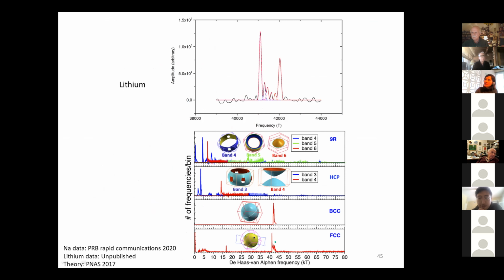So that's one of the things that we get inspiration from. But really the main reason that we're looking at these is way beyond that. We really want to understand what the Fermi surface of these metals looks like and how it changes with pressure. Fermi surface nesting is one of the ways that it is thought these metals become superconductors. Lithium becomes a superconductor. I think Warren Pickett had a paper on that. And it's very nice to see if we see this kind of Fermi surface nesting where the superconductivity starts.